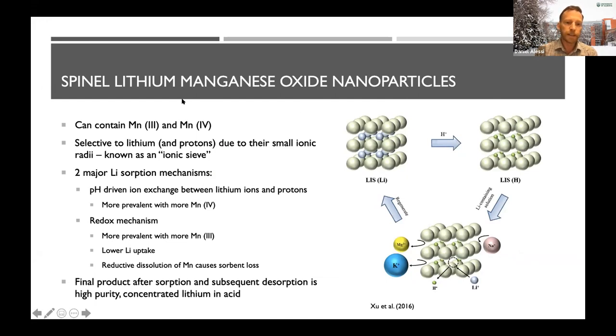So they can contain two valent states of manganese, manganese 3 and manganese 4. Manganese 4 is the most oxidized version of manganese. If I made an analogy in iron, if you have a car, it's made out of zero valent iron. So iron metal is Fe0. The oxidized form of that when you have rust is iron 3. And so this manganese 4 is the analogy to that. It's the completely oxidized, stable in the presence of oxygen form of manganese.